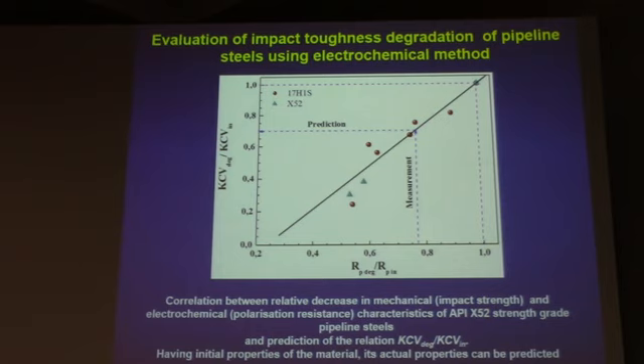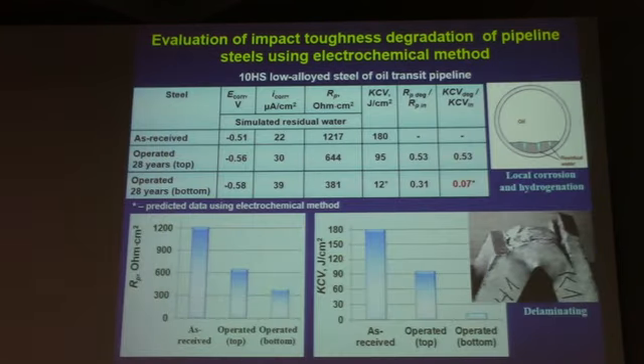And in other cases, we propose to use a metal with minimal operational degradation as a reference material. And here I presented an example of application of the electrochemical method for evaluation of degradation degree of oil pipeline steel after 28 years of operation. And in this case, we should compare not only as-received material and the operated one, but also different sections of operated pipe should be distinguished due to a possibly more intensive degradation degree of the bottom section steel due to hydrogenation caused by corrosion in residual water.